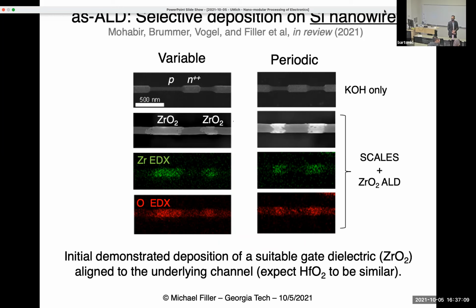So on wafers, it works pretty well. On nanowires, it's trickier. So these are two different nanowire types. And here we've shown that we can put zirconia, in this case another dielectric, not hafnia, but zirconia, down in the regions where we had lightly doped P, not heavily doped N. And we can change the dimensions of these regions, and we change the dimension of the zirconia that's wrapped around them.